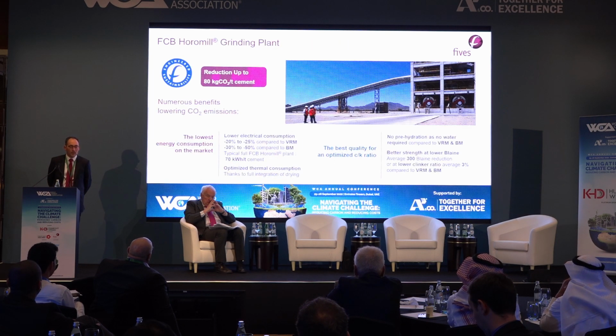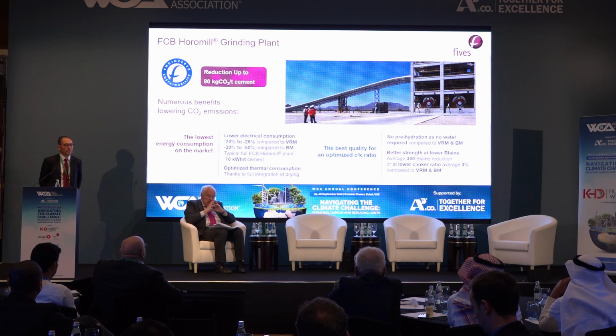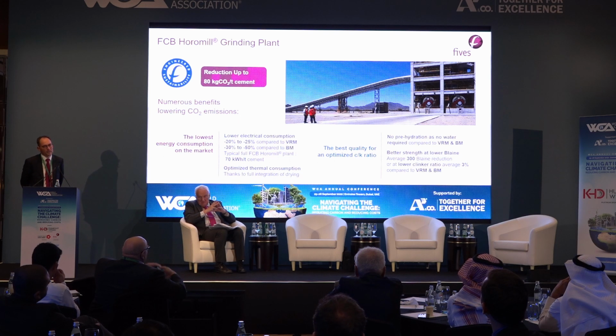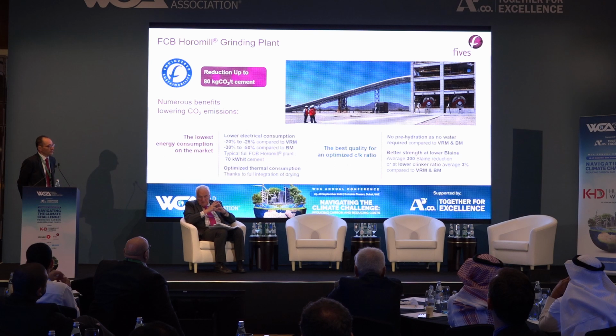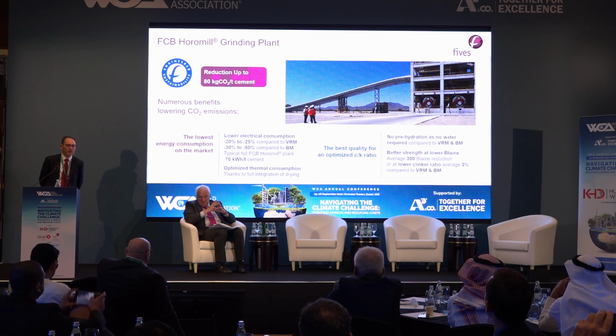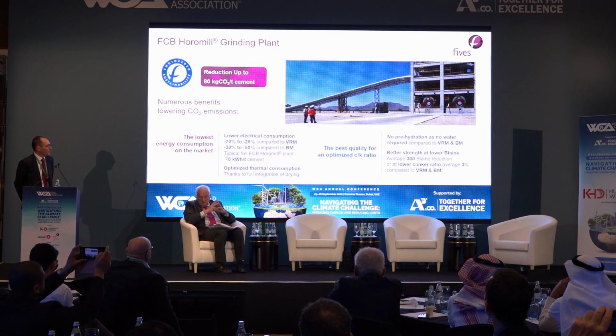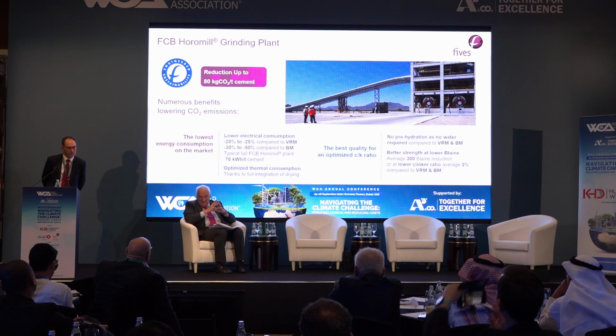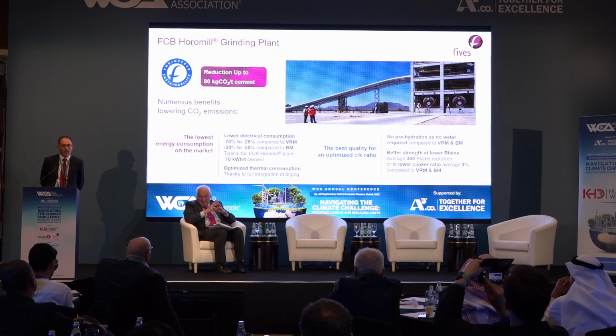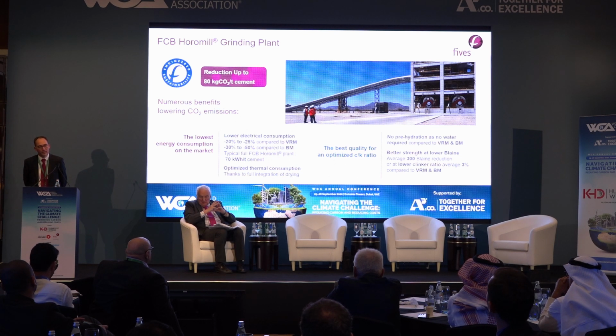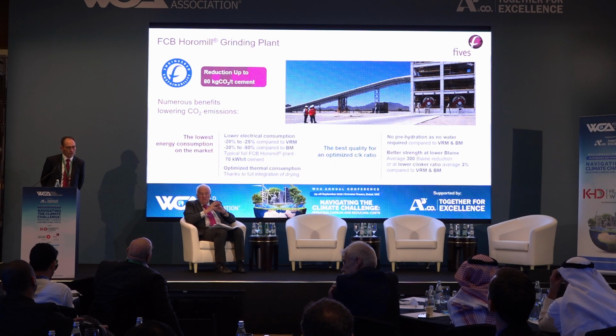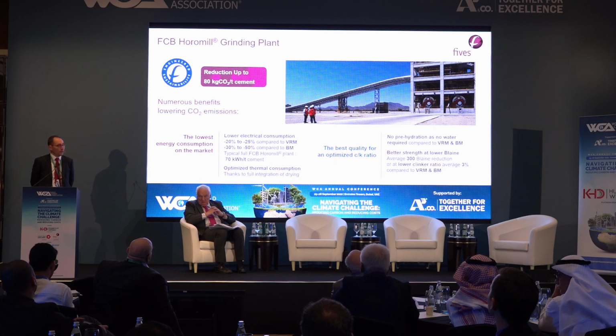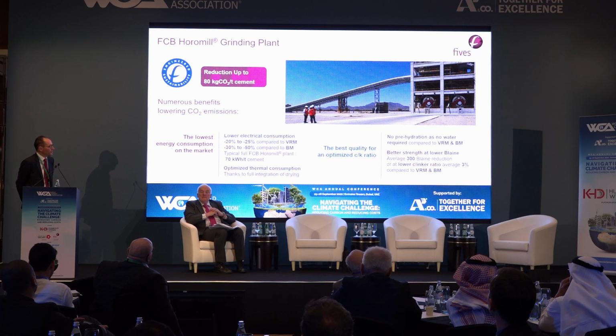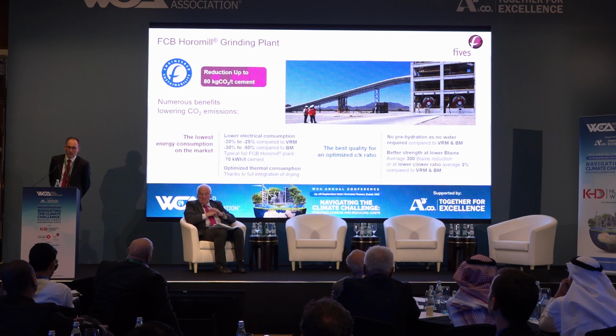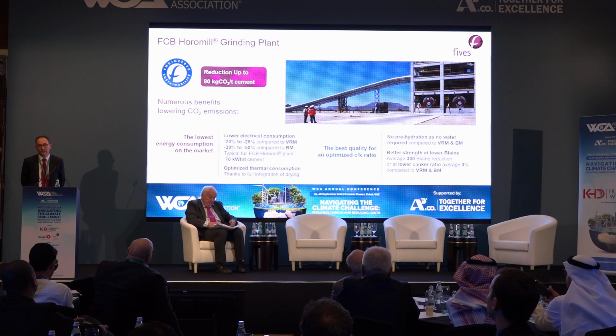So if we go to the grinding plant with Horomill, the mill was developed in the 1990s, so we have more than 20 years of feedback now. For this presentation and this purpose of CO2 reduction, we could split the advantages into 2 families. One is related to energy consumption. As soon as you produce electricity with fuel, gas, or coal, you emit CO2 when you use electricity. And we achieve significant savings compared to other known technologies. To such an extent that a cement plant built by FCB with FCB Horomill at raw grinding and cement grinding consumes only 70 kWh per ton of cement.